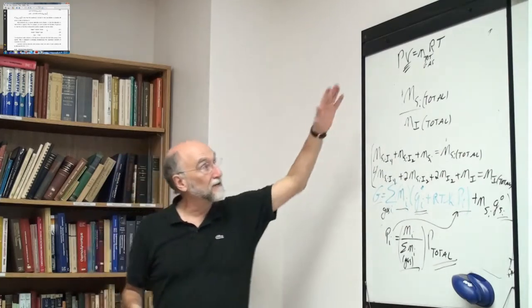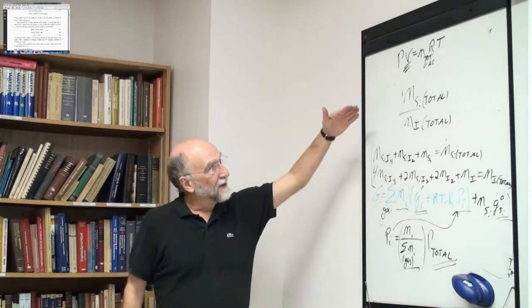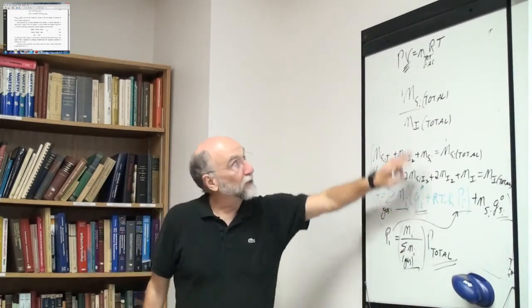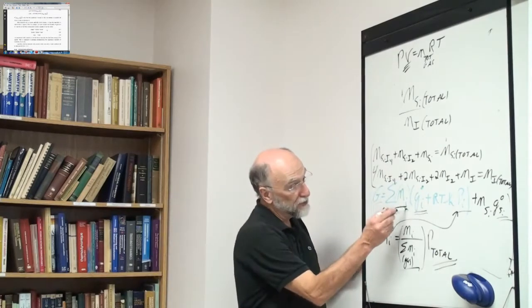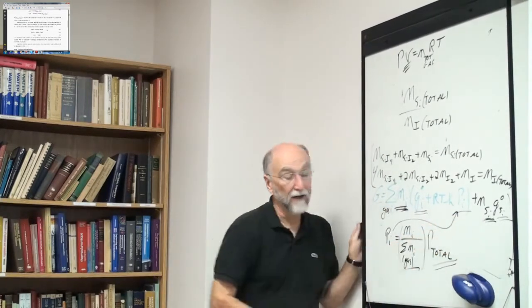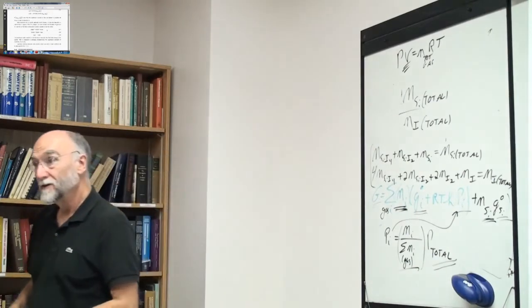Still, it's the same thing. Given enough constraints to properly constrain the system, generally mass balance and a total pressure or total volume constraint, you minimize the total Gibbs energy, and the mole numbers you get, Ni here, are the mole numbers at equilibrium. That's how FactSage works.